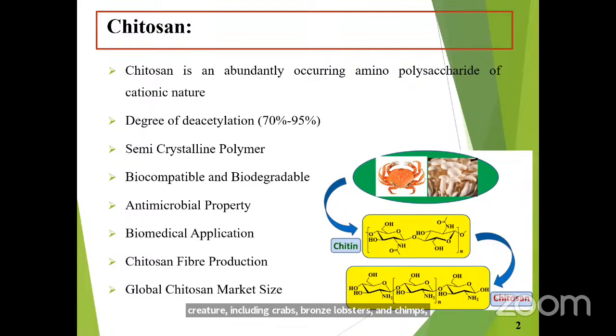Chitosan is a high molecular weight polymer composed mainly of monomers linked D-glucosamine and N-acetyl-D-glucosamine. The ratio between D-glucosamine and N-acetyl-D-glucosamine is the degree of deacetylation, which is really important in terms of chitosan. The deacetylated units have a typical degree of deacetylation between 70 to 95% and a molecular weight which varies between 10 to 1000.